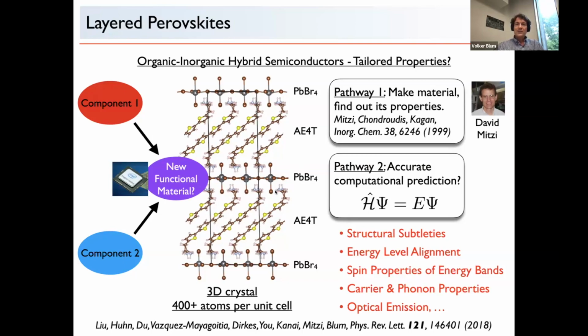We have to, because the semiconductors deal with the alignment of energy levels. So if electrons, for instance, are lower energy on the organic, that's where the electrons will go. If electrons are lower energy on the inorganic, then they'll go to the inorganic. And that will change the properties of a semiconductor drastically. Similarly, it turns out you can break the symmetry. So you can make these materials, for example, with chiral molecules that breaks inversion symmetry. And suddenly you'll get energy bands that have a defined spin expectation value. And so you can explore spin properties and also spin transport properties in the materials.